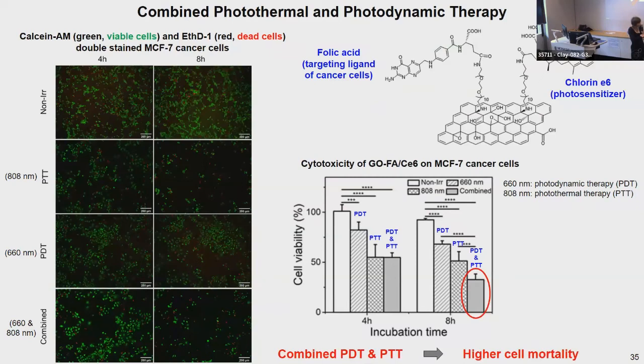So to make it short, let's look at the 8-hour incubation time. When we performed the single photodynamic therapy, you can see that the number of viable cells decreased. It decreased even more when we performed the single photothermal therapy. And when we combined the two, you can see that the cell viability was much lower. So indicating that by combining the two laser irradiations to perform the double therapy, we could induce much higher cell mortality. So now the next step is to perform in vivo experiments to treat tumors.